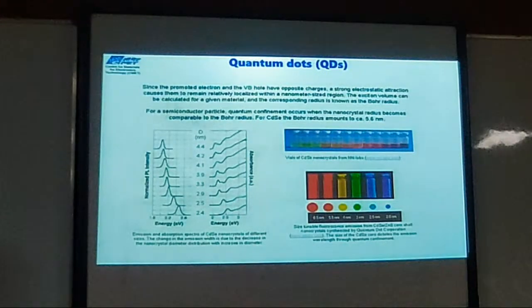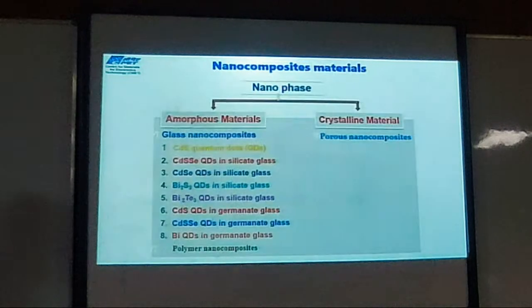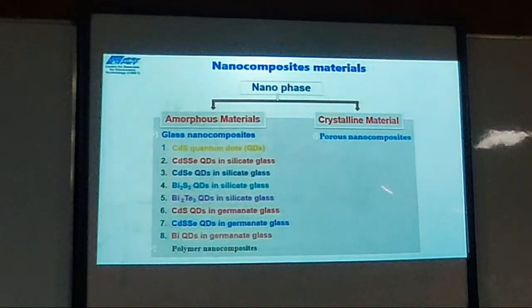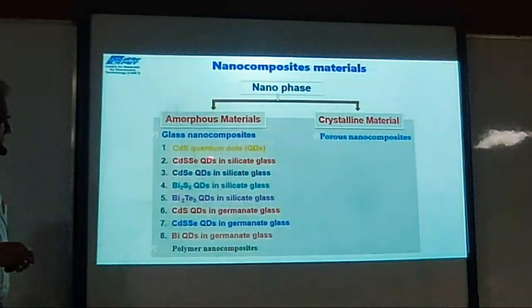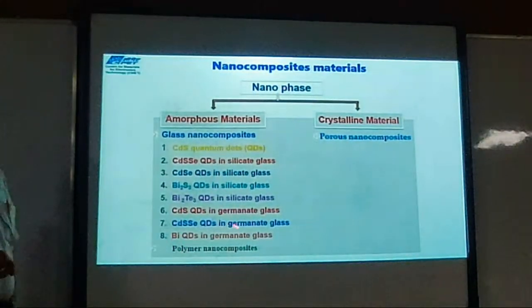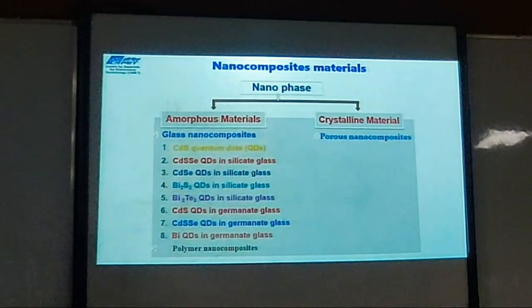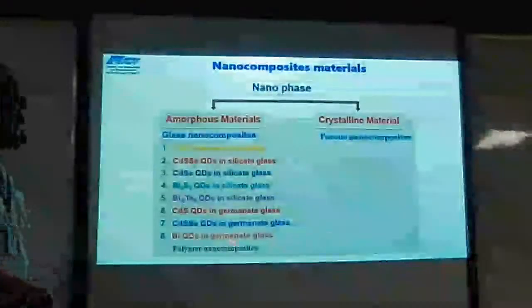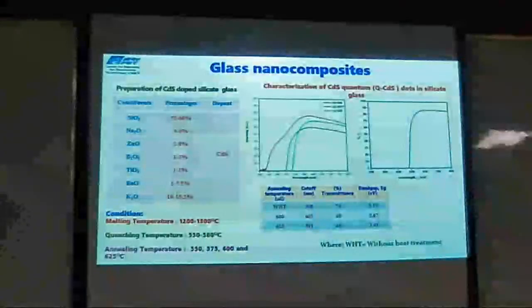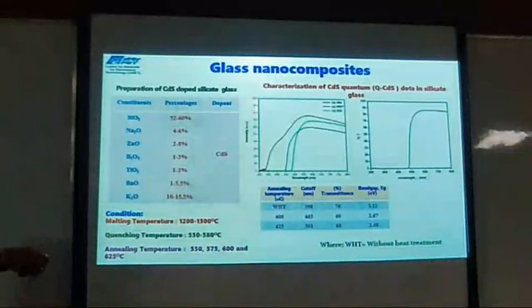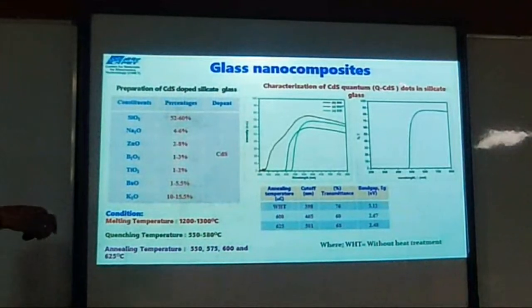This work is already going on. Whether we can have them in polymer, we can have glasses. So these are typical material glasses. We have CdS quantum dots in glasses, CdSSe quantum dots in glasses, CdSe quantum dots, bismuth sulfide, bismuth telluride, then bismuth quantum dots. Whether this kind of very low size material can be grown in glass melted at 1300 degrees centigrade, what we have to do is design the composition of the glass. In this glass, we can grow cadmium sulfide quantum dots.